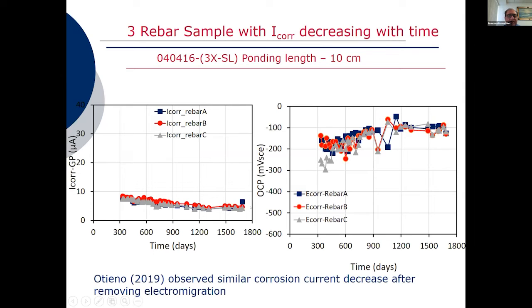change as a function of time for the corrosion current on the left, and this is for a 3 rebar specimen. In some samples, we observed what you see here, that the corrosion current decreased as a function of time. Otieno has reported that he observed that type of behavior on samples where corrosion was also initiated using an electromigration method, slightly different from what we did here, but still comparable.